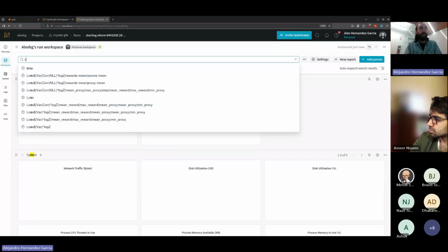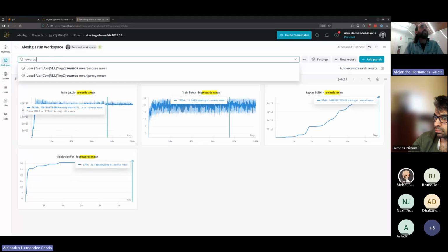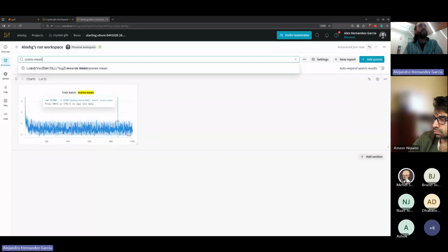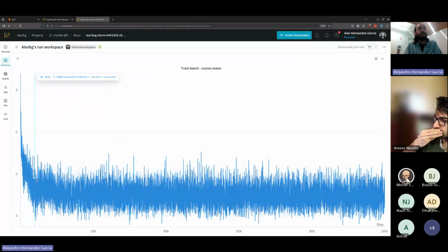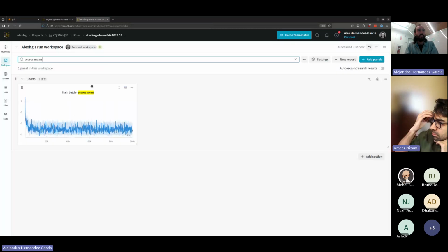Okay, and now we're going to see the rewards. Actually, I'm going to show the scores, because it's the formation energy itself. So the y-axis is the formation energy as predicted by the model. We can see that as we train very quickly, it's already going to minus 2 point something. This is not as low as it would get at sampling time, because here there is some replay buffer going on and some random actions that make it higher. But you can see that very quickly, it starts sampling crystals with very low reward. Then we train it for longer just to let it explore more and more. But very quickly, within minutes, it's sampling good crystals, meaning low formation energy.